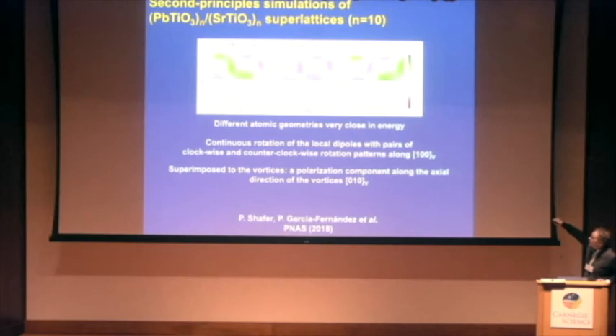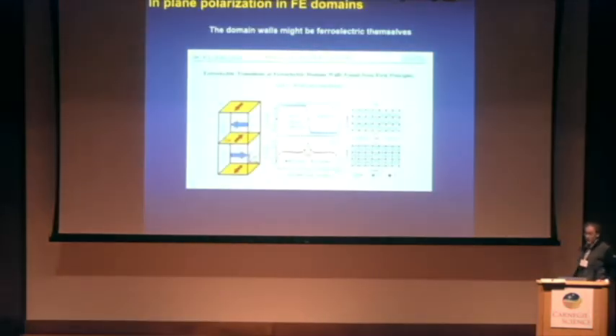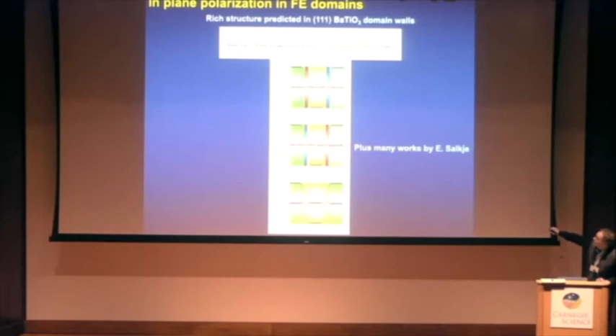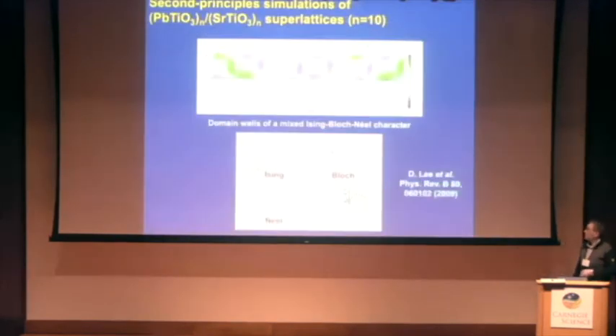So the fact that we have this component of the polarization here at the domain walls suggests that the domain walls themselves are ferroelectric. And this is a result that has been previously obtained, for instance, by Jacek Wojdel and Jorge Íñiguez in 180-degree domains in bulk lead titanate. So they were able to observe that the domain walls themselves were able to sustain a component of the polarization. Also, the group of Hlinka detected a very rich phase diagram predicted in these 111 barium titanate domains, and there are many works by Salje. So it's very well established now that the domain walls themselves may be ferroelectric.